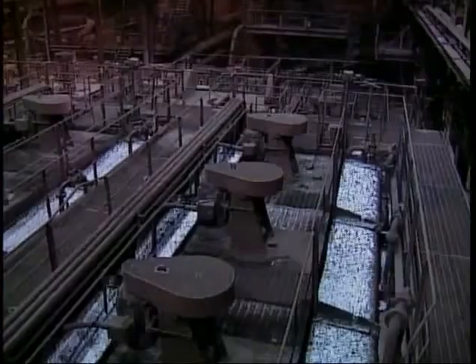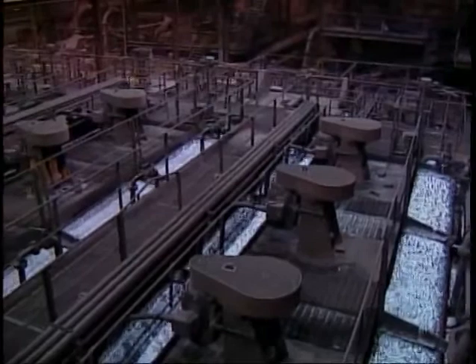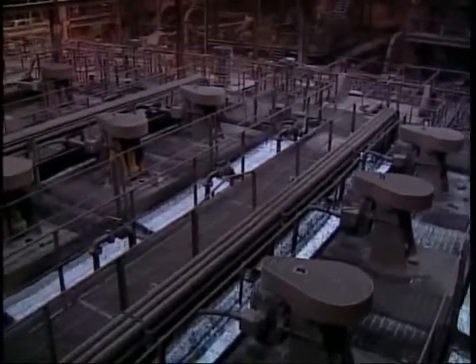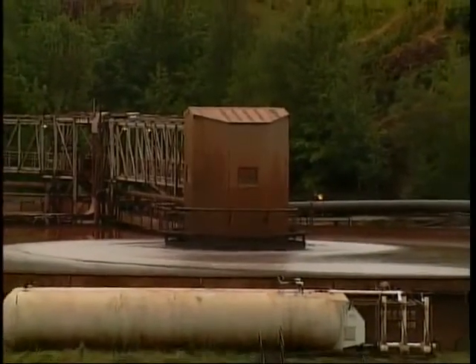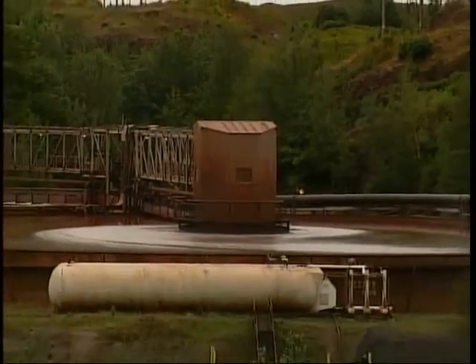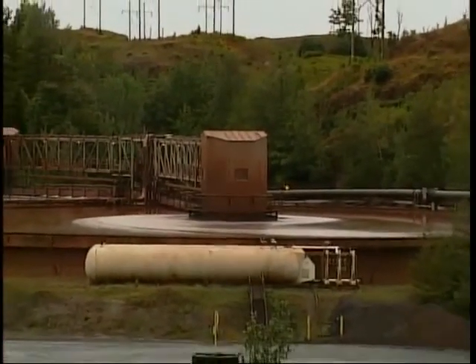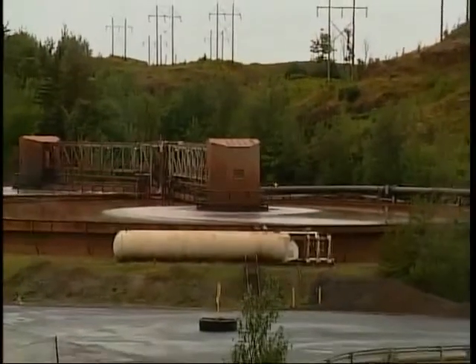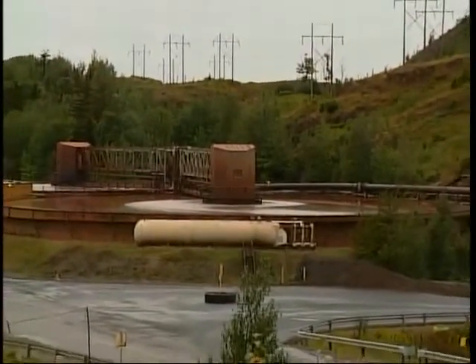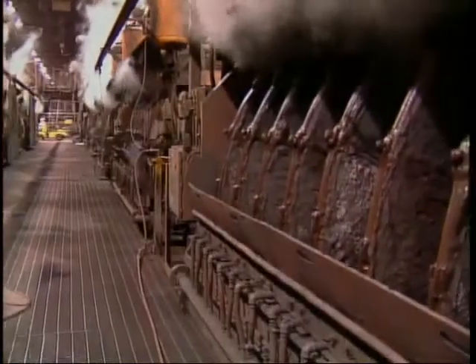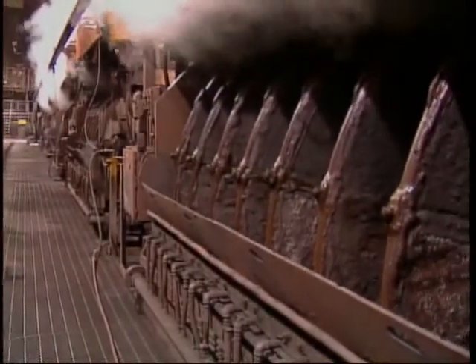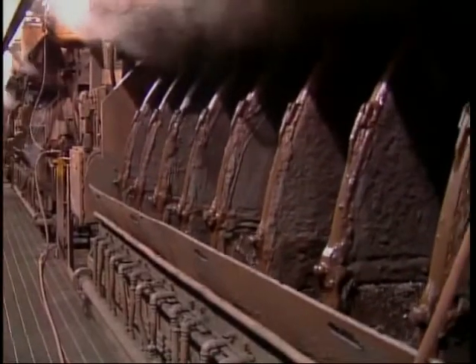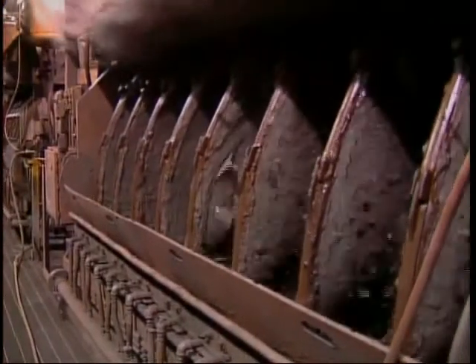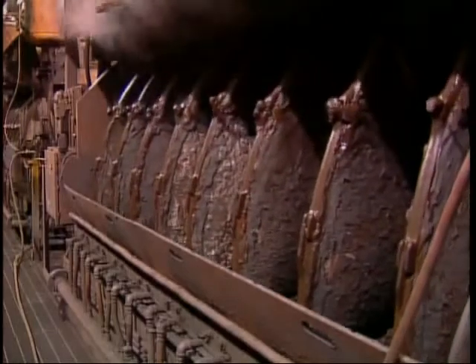and is washed away. At both Empire and Tilden, the ore slurry is also upgraded by a flotation process and is sent to large concentrate thickening tanks to begin the process to thicken the slurry and remove the water. At this point, the magnetite and hematite process remains the same throughout the rest of the plant. The thickened concentrate slurry is sent to vacuum disc filters, where much of the remaining water is removed, leaving a high-grade iron ore concentrate, about 65% iron, which is conveyed to the pelletizing plant for final processing into pellets.